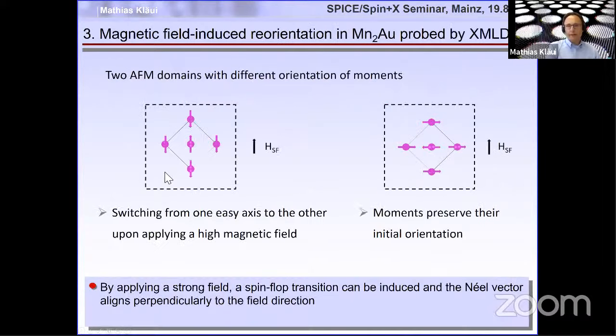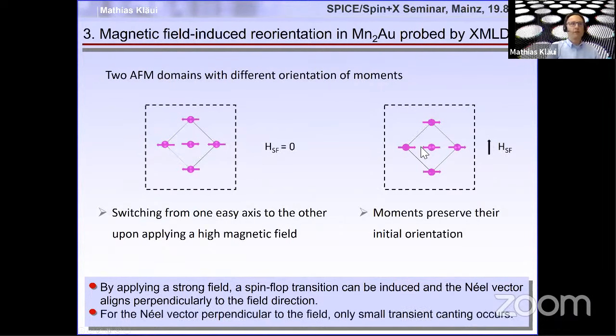So here again is the example of our antiferromagnet. If I apply a strong field, then we see that the sublattices orient perpendicular to the field. And if they are already perpendicular to the field, then they just cant a little bit in the applied field. And we measured the X-ray magnetic linear dichroism. So you see here the canting of the sublattices with the applied field.